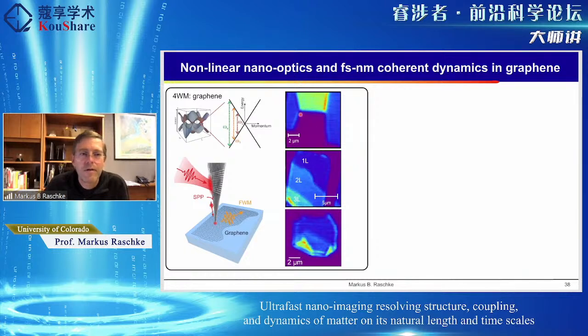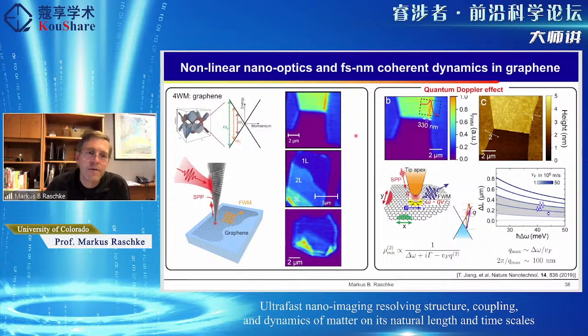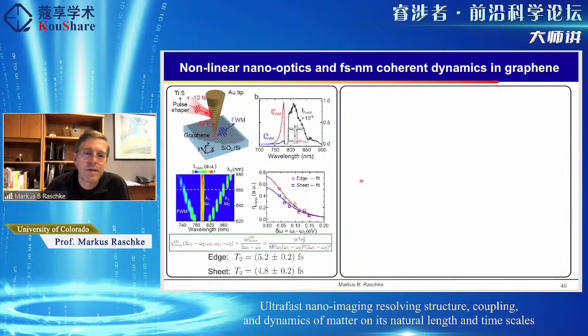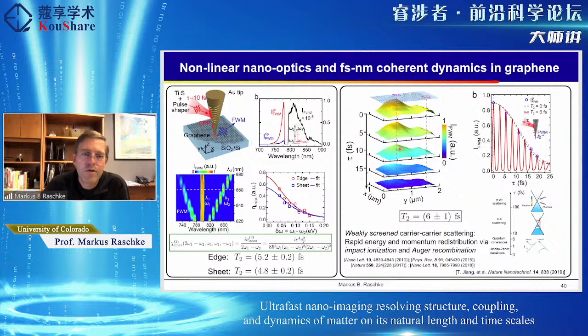So now here you're seeing the temporally integrated four-wave mixing signal on sheets of graphene: monolayer, folded, bilayer, trilayer. And there is, in fact, and I don't have time to talk about this, in the nanoscale, a difference in the nonlinear optical response. We're getting non-local effects of the nonlinear response. But what I want to show you is really just the time resolution. Then when we image here the edge of a graphene film as a function of time delay, we see there is not only spatial heterogeneity in this decay, but we see extremely fast electronic decoherence in graphene.